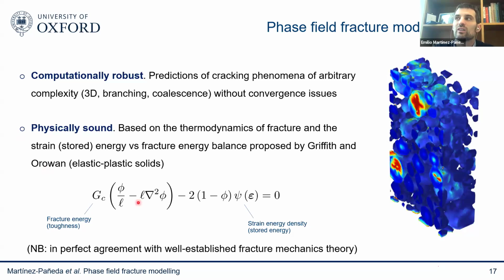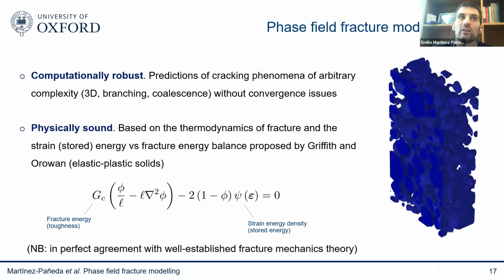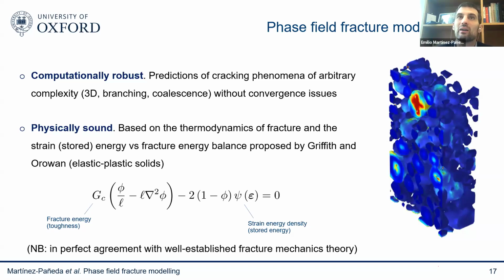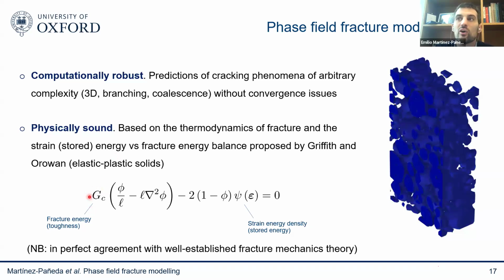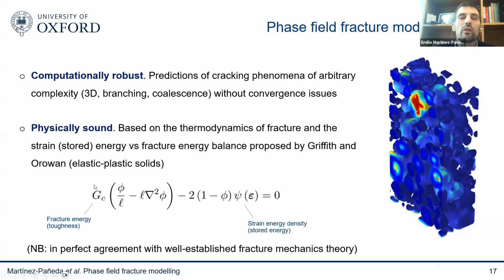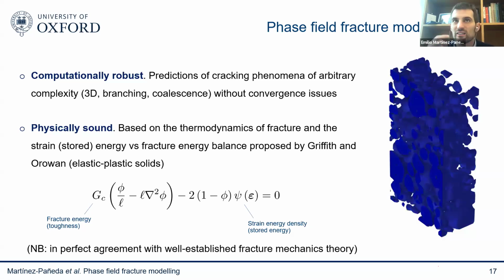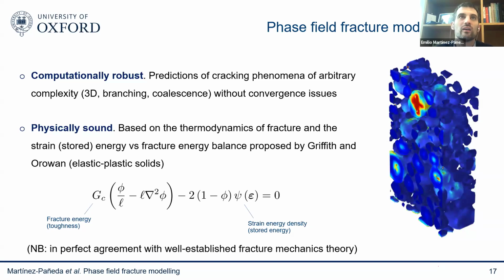And it's also a method that is physically sound. It's all based on thermodynamics of fracture, the balance of storing energy versus releasing energy to propagate a crack. And the beauty of being based on the thermodynamics of fracture and this framework that Griffith and Orowan established is that it's in good agreement with fracture mechanics theory. I will discuss that in a minute, but this is quite important because when we work with industry, they know that they can use this method. They know the inputs to this method are values that they know. They work themselves with fracture toughness, so they know what is the fracture toughness of their material. And they know that the method is going to give them the same answers as the simple engineering standards that they're using for the simple cases where engineering standards apply. But then they can use this method that seems consistent with everything they know for more complicated problems.